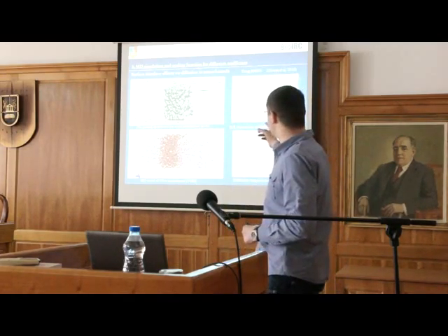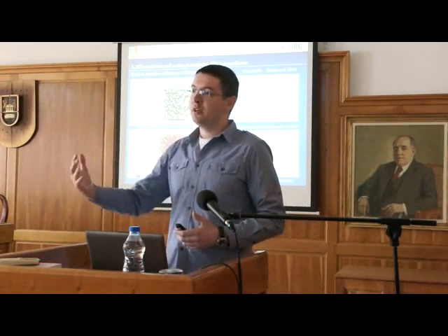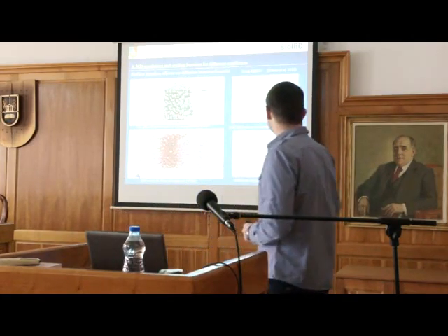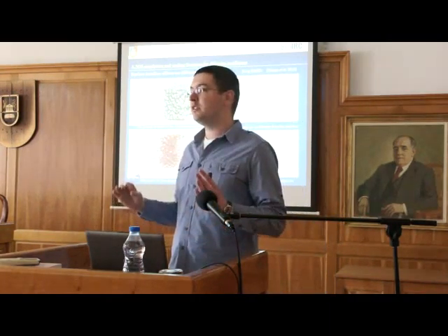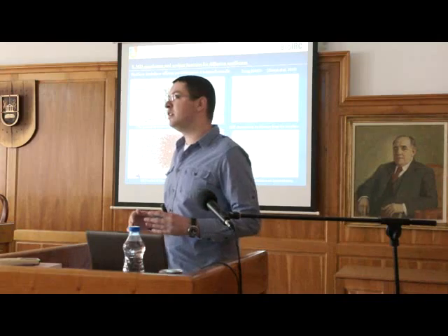So if you can see from this picture, if we are close to the surface, at a distance between 0 and 1, then there are some attractive forces from the surface, so movement is constrained. If we are far enough from the surface, for example, at 4 nanometers, the molecule is not affected by the surface, so it is free. It is free to diffuse in the system.